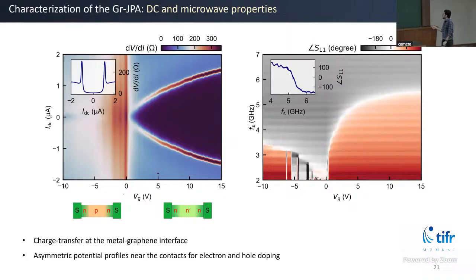Right, so after you see that the devices are working in DC transport, next we move to microwave measurements. In microwave, what we do is measure the reflection coefficient, which is S11. It's a complex quantity, so I'm plotting the phase of it. And what you are seeing, this white color is the resonance frequency of our resonator.